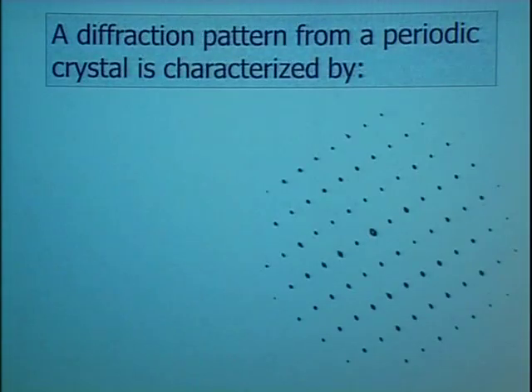Let's now go to the diffraction space, which we call the reciprocal space. Reciprocal space is a mathematical space in which the diffraction peaks exist. And this is an electron diffraction. What you see here is this center point is the transmitted beam, and all the other points are diffracted beams. What we do in an electron microscope, we shine an electron beam on a specimen, and we can tilt the specimen and obtain diffraction in each and every direction. Part of the beam goes through, this is a transmitted beam, and all the other beams are diffracted.